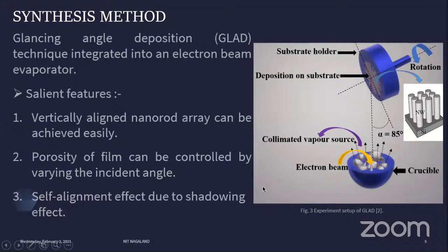So the synthesis technique employed in the work is glancing angle deposition technique, which is incorporated into an electron beam evaporator. This GLAD technique is an extension of OAD, oblique angle deposition technique. Some of the advantages GLAD offers over OAD is that vertically aligned nanowires or nanorods can be achieved easily in comparison with other techniques. Also the porosity of the film can be controlled by varying the incident angle of the vapor flux. And the third advantage is that due to the self-alignment effect, which is due to shadowing effect, we can achieve a vertical nanowire as shown here. Also, the GLAD technique is a simple technique compared to other prominent CVD and PVD techniques, as well as it is a catalyst-free technique.